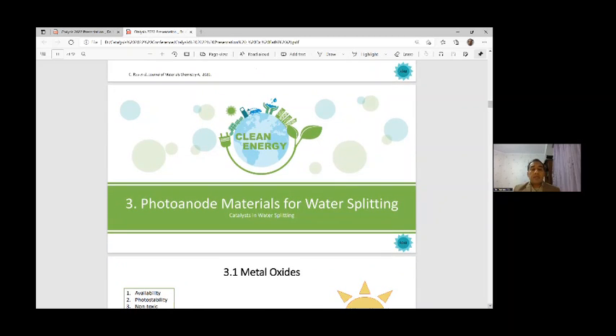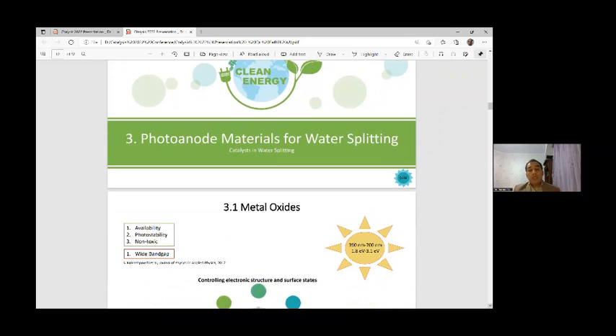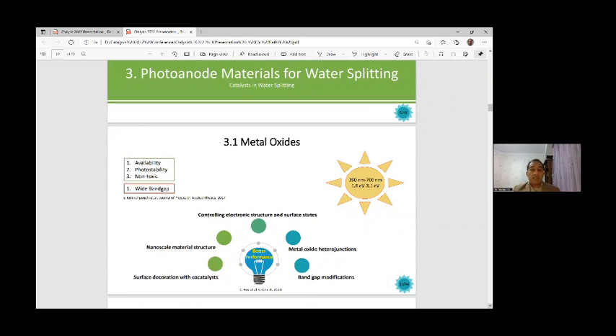Here I present a talk and short literature review about photoanode materials for water splitting. Firstly, I refer to metal oxides. Metal oxides have advantages such as availability, photostability, and non-toxic behavior, but usually we face the issue of a wide band gap. For better performance in metal oxide water splitting systems, using metal oxide in the structure of the photoanode in the PEC water splitting system, we have to do, for example, controlling electron structure at surface states and nanoscale material structure. We face these challenges and issues.